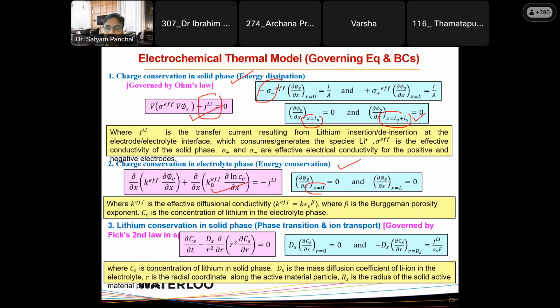where boundary conditions at x equal to 0 and x equal to L are provided over here, where K effective is the effective diffusion conductivity, which is given by K into epsilon to the power beta, where beta is the Bruggeman porosity exponent, and C is the concentration of lithium in the electrolyte phase. Then the third governing equation is lithium conservation in solid phase, that is typically phase transition and ion transport, and that is governed by Fick's second law in spherical coordinates, which I explained earlier.